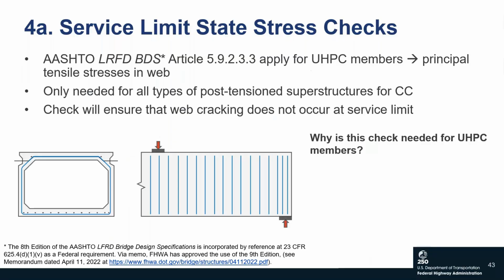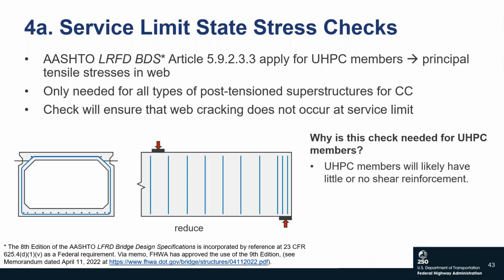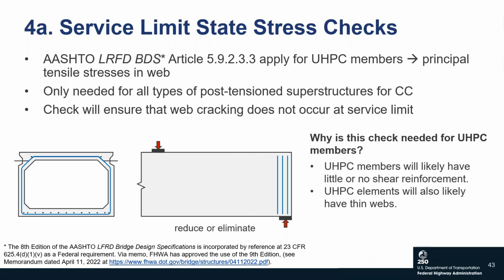So as I said before, one of the differences with UHPC at the service limit state is that we need to check these web shear stresses. And the reason that we need to do that is because our UHPC members are likely going to have little or no shear reinforcement. So this is one of the big benefits of using UHPC. We can either reduce or even completely eliminate the shear reinforcement in our beams. Also, our UHPC elements are likely to have thin webs. And because of that, we don't want them to crack at the service limit states. So this check helps to ensure that.